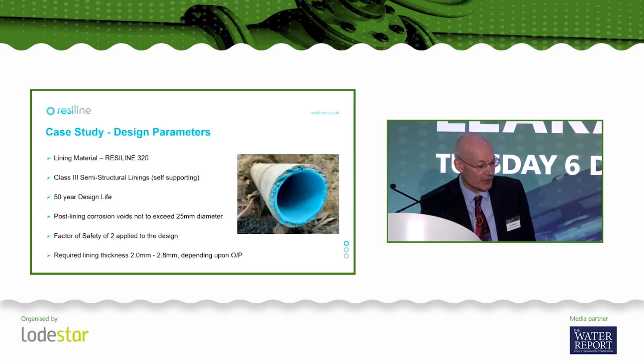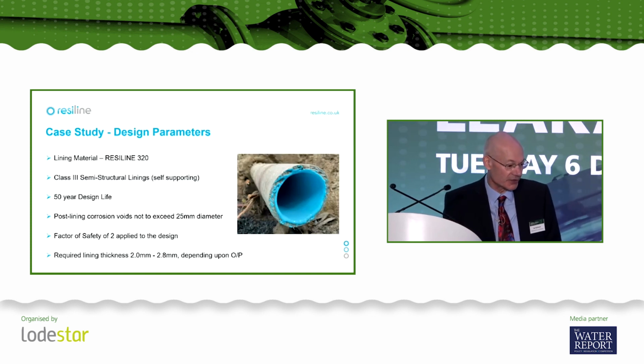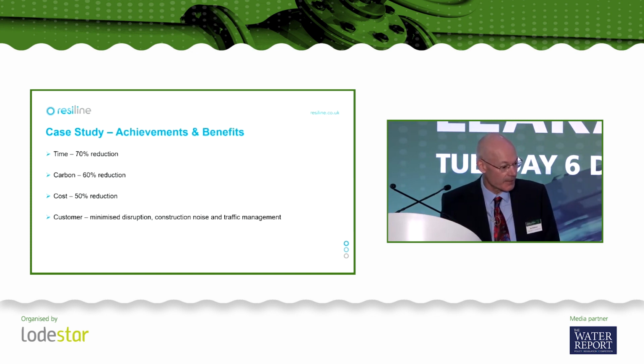So the material which was used was Resiline 320. These linings were all designed to be class 3 semi-structural linings, so self-supporting and not reliant on adhesion. All designed with a 50-year design life, and the assumption was that any corrosion voids forming post-lining, as a result of ongoing external corrosion, would not exceed 25 millimetres diameter. A factor of safety of 2 was applied to the design, which resulted in lining all of this being able to be accomplished with lining thicknesses ranging from 2 to 2.8 millimetres, which could all be applied in a single pass of the lining head.